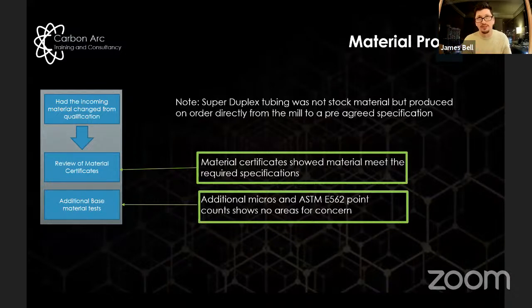So that then got us, right, our weld procedures are good. Our welding controls, we believe, are still adequate for what we need to do. Let's look at our materials. Where are we going wrong here? Now, as I said earlier, all of the materials are produced but for order by the mill, and there's full control of that. We know exactly how that material is going to be produced, what it looks like, how it's tested. All that's done in a huge amount of detail before we get it as the umbilical producer. So what's wrong? Quick, have a check, see where we are. Now, the material certs were correct. We did additional tests to make sure the material certs were correct. And everything, again, was fully in order, but we have this very, very high failure rate.